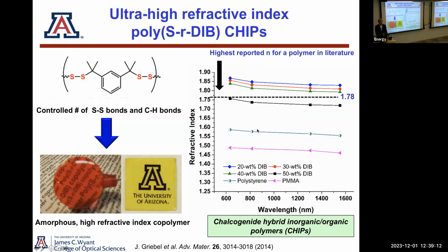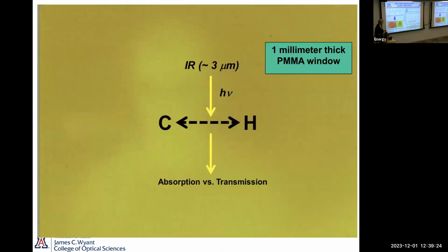You can see the refractive index is very high. Ordinary polymers, you can see PMMA down here, polystyrene down here, and we're up here, and I'll show you even higher ones. So we wanted to see, though, are we really more transparent in these longer infrared wavelengths? So this is in the 3 micron region. So you're getting into thermal imaging kind of. Thermal imaging is really more focused in the long wave, around 8 to 12 microns. But you still have thermal aspects in the mid wave from 3 to 5 microns.